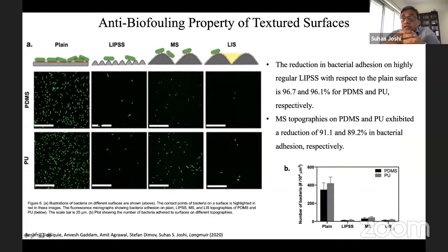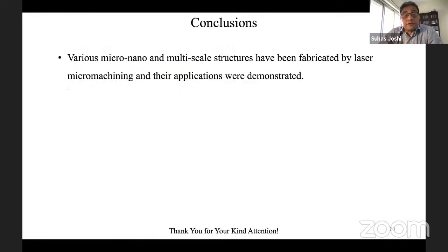Many of these properties, like contact angle or hydrophobicity and anti-biofouling properties, primarily depend on the initial microstructure, the initial texturing of the surfaces. So if you simply test the contact angle, that itself gives you a good idea of whether it will have hydrophobic properties, sliding durability, and so on. But here we have tested anti-biofouling properties.